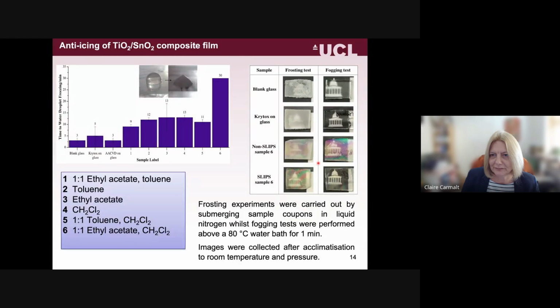So did it work? Well, we did quite a few different experiments. What we did was the same reaction, so the titanium isopropoxide and the butyl tin trichloride, but we varied the solvent that we used for the AACVD reaction. And you can see we had 6 different variations. Then we measured how long the water droplet took to form ice, and we compared it to the blank glass substrate. We compared it to the lubricant just on the glass, and we compared it to the plain AACVD film that we deposited with no lubricant on top.